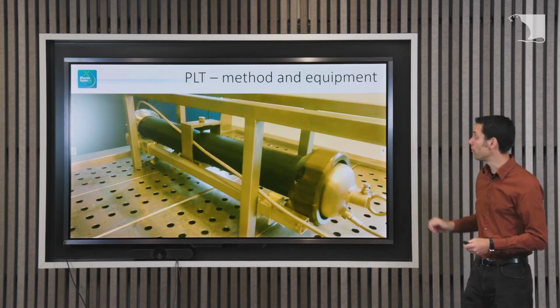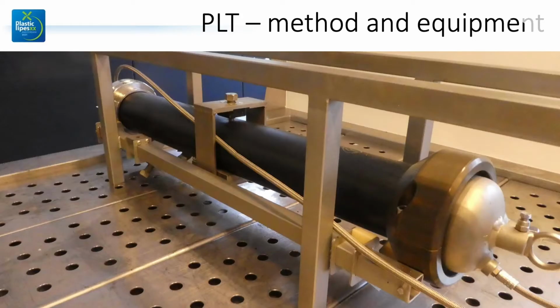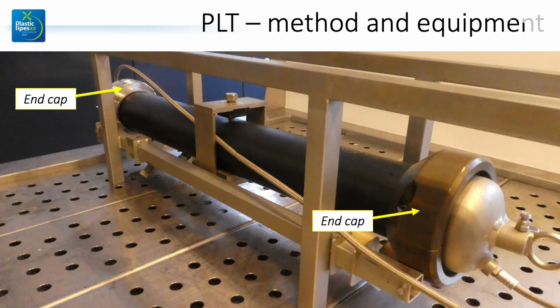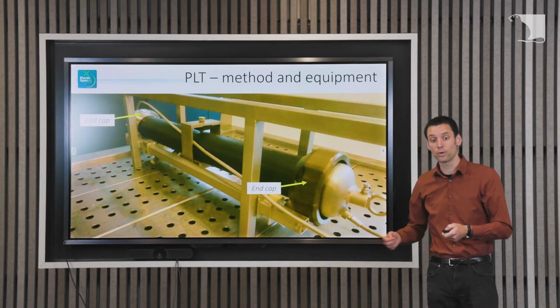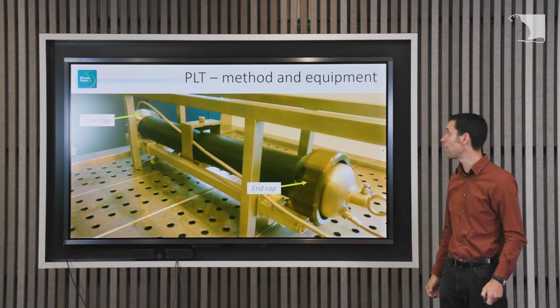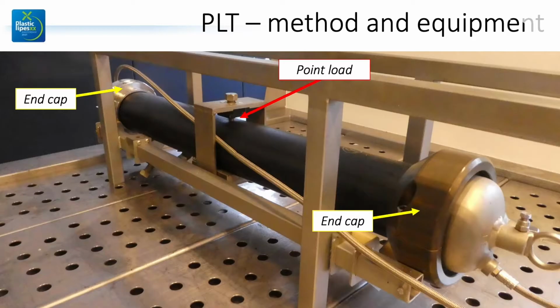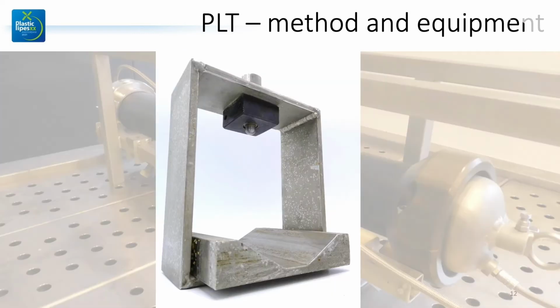So this is a picture of our test setup. So you see two end caps of the pipe, which have those hoses to circulate the detergent. It also has a connection for pressurizing the pipe. And we have the point load. Here you can see it, and of course the support. So it's difficult perhaps to see. So here's a bigger picture. So this is where the pipe is placed inside. The point load has a tip radius of 5 millimeters, so the diameter is 10 millimeters.